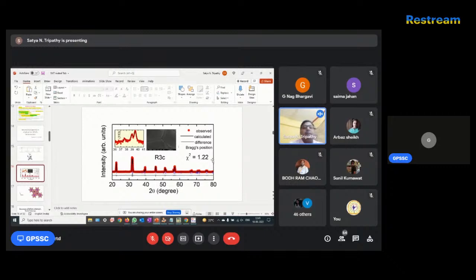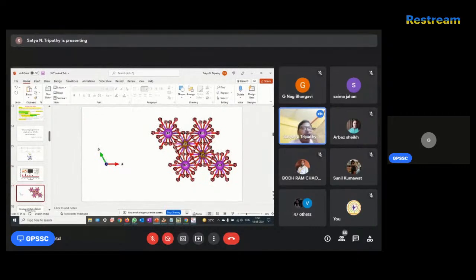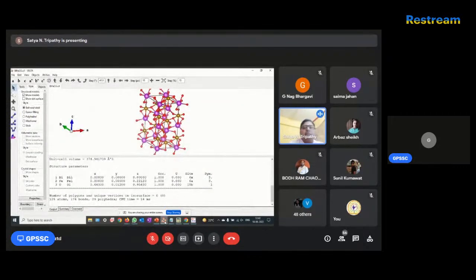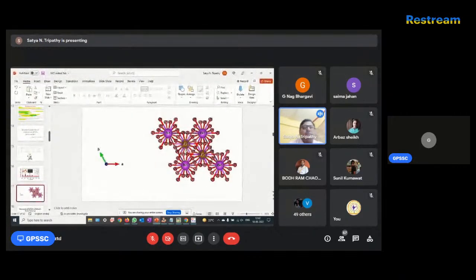This is the way the refinement was carried out, and this data has been reported in Materials Chemistry and Physics. This data matches the previous reports. So we confirm that if the experimental data fits the theoretical data, then yes, this is the crystal structure. These are the lattice parameters. This is the crystal structure of the sample you are going to get. If you want to show this in a paper, it is fine, but you can easily do it with available software called Vesta. You can easily change the box size and present it. This does not matter that much to me.